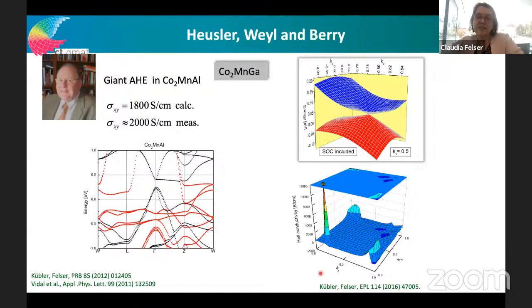In 2016, we finally understood, after all this knowledge about Weyl semimetals, crossing points and the contribution of this crossing point to the Berry phase, Berry curvature, that this is the origin. Here you see the Weyl point in Co2MnGa and this nice peak here in the Berry curvature in this compound Co2MnGa and Co2MnAl. So this explains this really enormous high value in the Berry curvature, which is unexpectedly high.